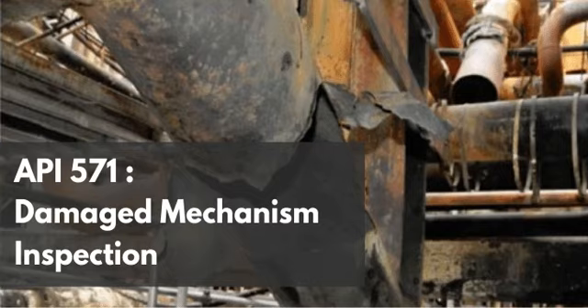I really want to focus on that temperature band. 1200 to 1225 degrees Fahrenheit. That is a microscopic 25-degree window. It's incredibly tight. If you are heat treating a massive heavy wall fractionator spool piece in a shop furnace or wrapping ceramic heating blankets around a field tie-in weld out in the pipe rack, maintaining a delta of 25 degrees across the entire weldment is an incredibly difficult thermodynamic challenge. It is a massive headache for field crews.